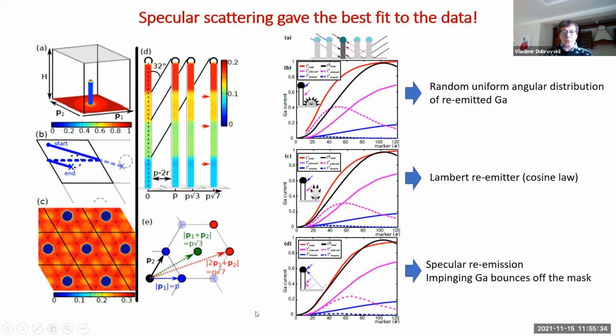And then to fit the data, several models for the re-emission were considered. First of all, surface diffusion was ruled out because it required unrealistic time dependence of the chemical potential driving. So the conclusion was that the main contribution was the re-emission of gallium from the mask. And then it was found that the best fit could be obtained with just specular emission from the mask, rather than Lambertian scattering or random uniform angle distribution of re-emitted gallium. Meaning that gallium atoms impinging on the mask surface just bounce off the surface at the same angle, and then they contribute into the nanowire.